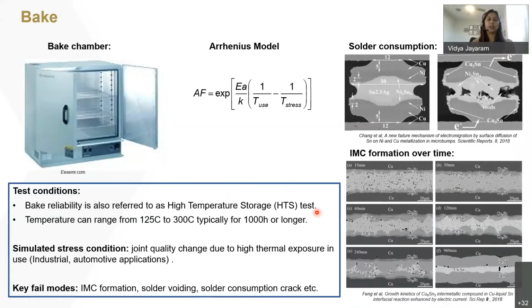Bake is interesting because it does simulate a thermal stress condition, kind of similar to HAST and thermal cycling. However, it looks closely at the joint quality due to high thermal exposure. So for example, with high temperature and an extended period of time, if you want to accelerate the failure of the solder joint, you would see over time the bulk solder gets consumed to form the IMCs, and you'd be able to detect that with a bake type of stress test.